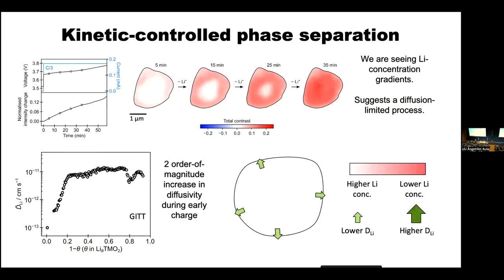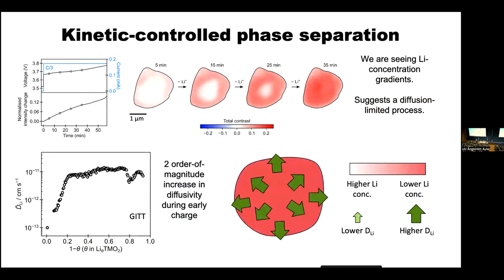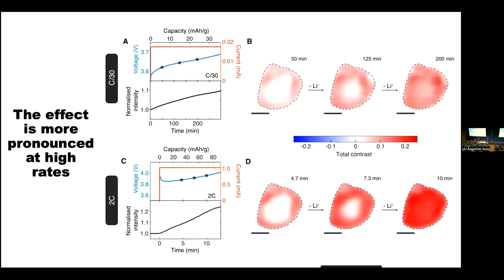I've touched on this before. You start off with a phase initially that's very poorly conducting because it's full of lithium. You start pulling lithium out of the edges. The mobility increases because you've got vacancies in the structure. It continues to be easier to pull stuff out of the red phase than the white phase, and it grows, and you have, again, this core-shell model. This is an example where you have a single phase that is a metastable two-phase. The lithium cobalt oxide was a true two-phase reaction thermodynamically. So there are subtle differences in the kinetics and thermodynamics, but remarkably related phenomena.